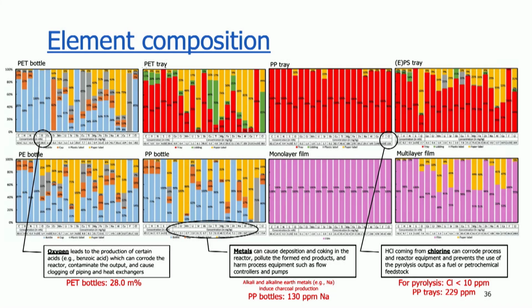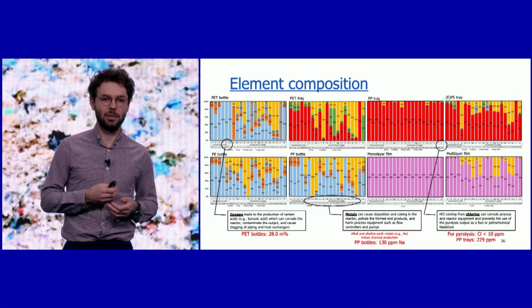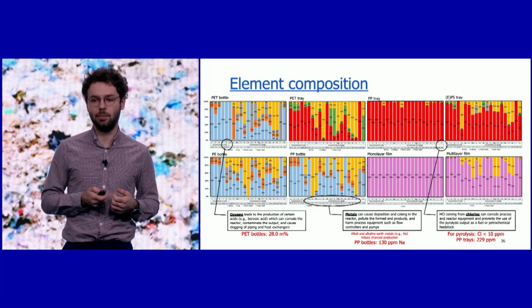A third thing that we analyzed was the chlorine content, and also here we saw quite high values. For instance, the polypropylene trays contain 229 ppm of chlorine, which is much higher than the threshold sometimes stated in the literature of 10 ppm.